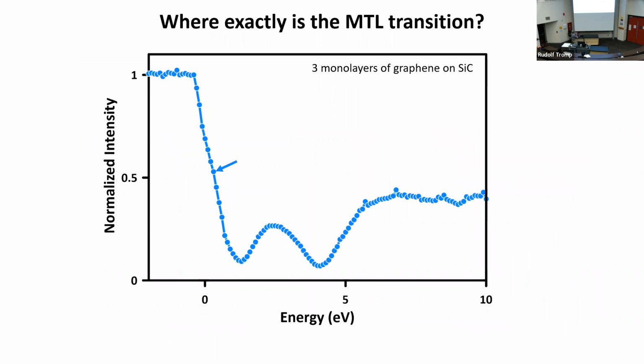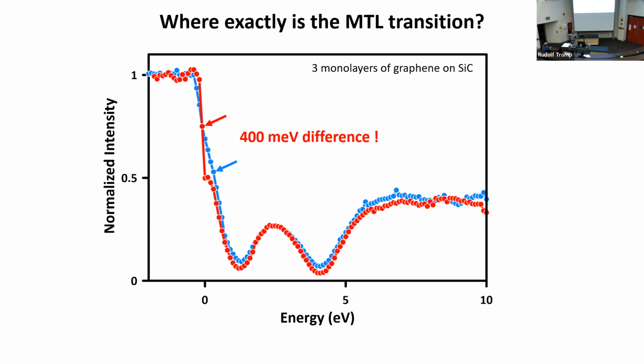Typically, we measure this electrostatic potential by measuring this transition from mirror mode reflectivity 1. And this again, you recognize this now, is on 3 layers graphene. And we say, well, the electrostatic potential is sort of given by the midpoint here, right? So we draw the midpoint and say, okay, it corresponds to what I called 0 eV here. This is unfiltered electrons. When I filter the electrons, you see the minima get deeper, etc. But more importantly, we see that there's actually a shoulder here, which in the blue data you can very weakly see, right? So we find that the half point is actually not here, but it is here. It is where we drop down to this plateau. And the shift is quite significant. It's 400 millivolt, which if you're interested in what the electrostatic potential is, if you think of chemical terms, it's a huge difference. The electrochemical potential differs by 400 millivolt between those 2 measurements.